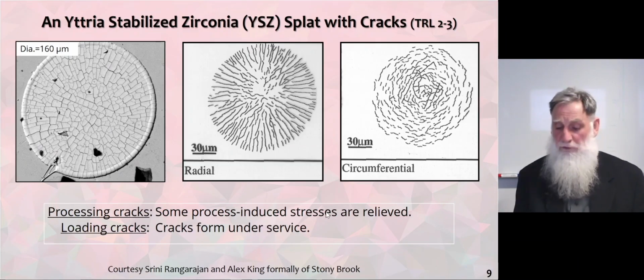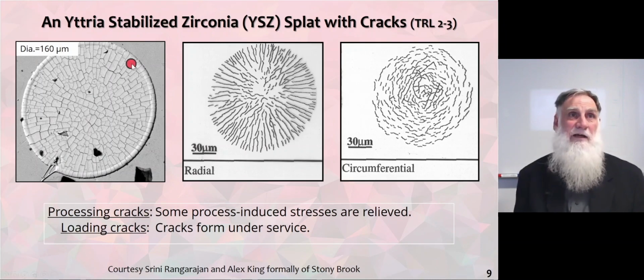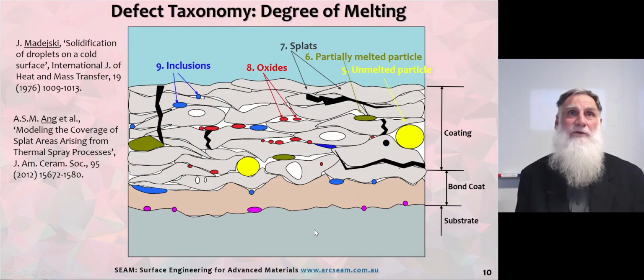Another work from Stony Brook University in New York also looked at singular splats. And here we have a single splat that has been interrogated by various image analysis techniques so that either radial cracks or circumferential cracks could be well defined. And the addition of these two crack networks gives rise to the ultimate properties of the whole structure. So processing cracks were induced and could be relieved by heat treatment, and then loading cracks form under service conditions.